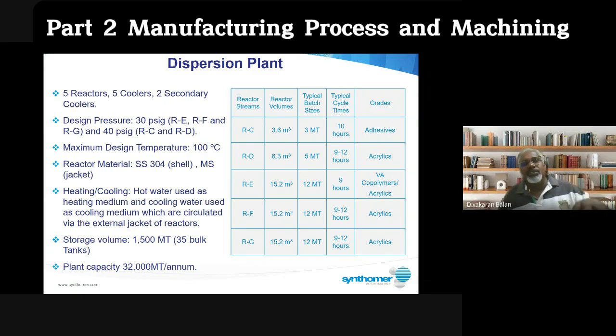So this process plant, polymer dispersion Kluang, we have 5 reactors. You can see here, 5 reactors. Reactors are the main equipment to polymerize the polymer dispersion. The other 5 coolers and 2 secondary coolers are supporting tanks for the reactors. When you end the process in the reactor, you transfer to the cooler to cool down, and add in some other raw materials before we can filter and move to storage.